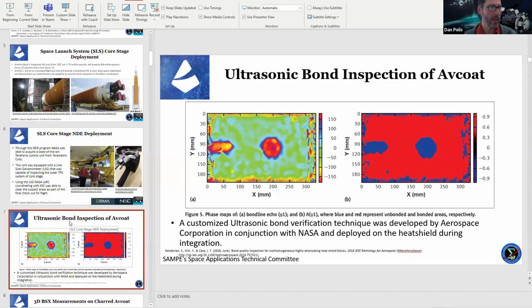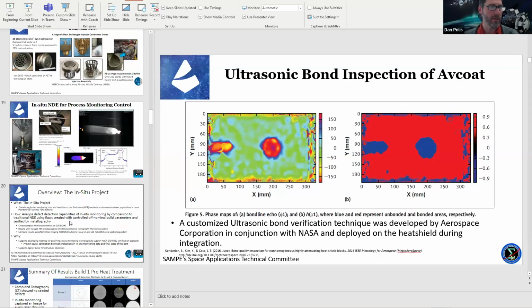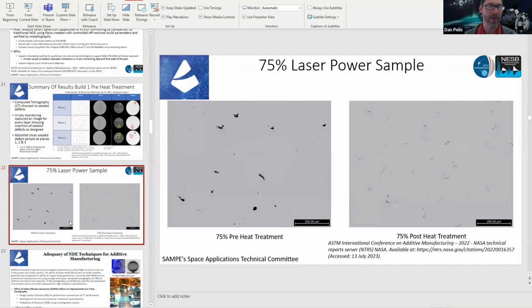Is a flaw that closes up after heat treatment with HIP, or not, still considered a concern if CT misses it? And how do you then quantify? These are the questions that we go to fracture control with, right? I do have a materials background, so the answer is, for the most part, yes. From an NDE standpoint, it's a definite. If there's still a defect there, but it's below what I can find, then you kind of got to talk out of both sides of your mouth. There is an inspection criteria that basically says a critical defect of this size is what you need to find. And that's how it's done.